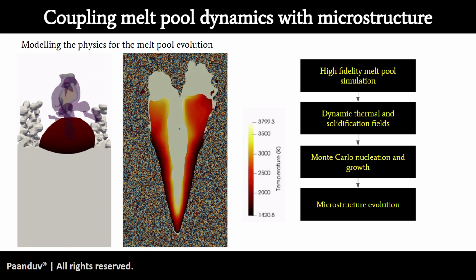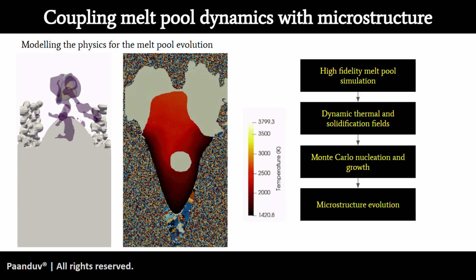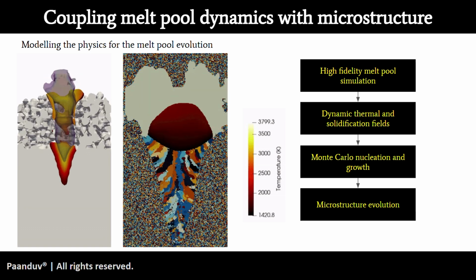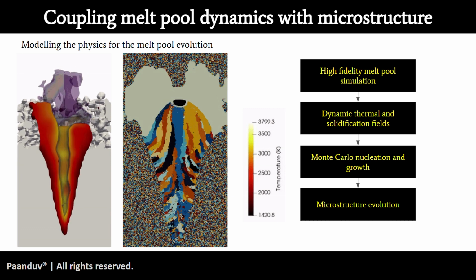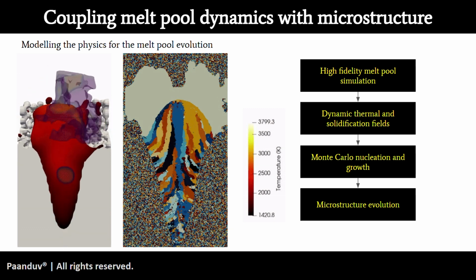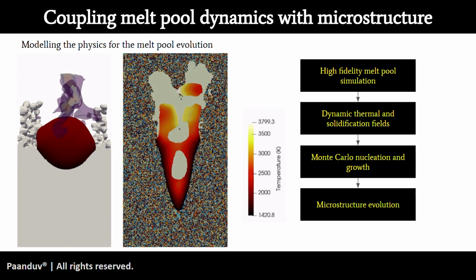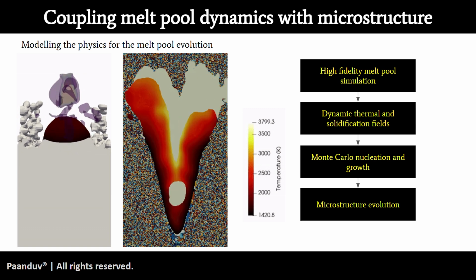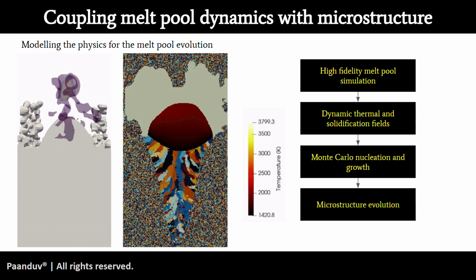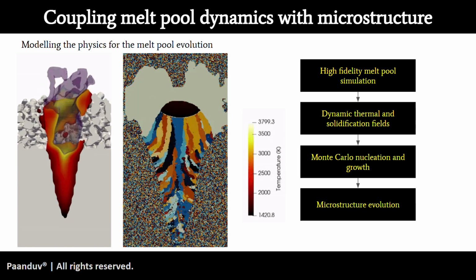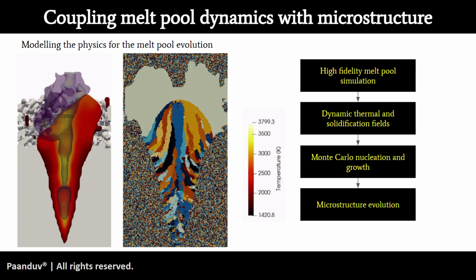So the flow of simulations is, you first run high fidelity melt pool simulations, then using the dynamic thermal and solidification fields, you predict the microstructure evolution. In the background, there's a Monte Carlo nucleation and growth model that is taking care of the grain evolution, grain initiation, and their growth.